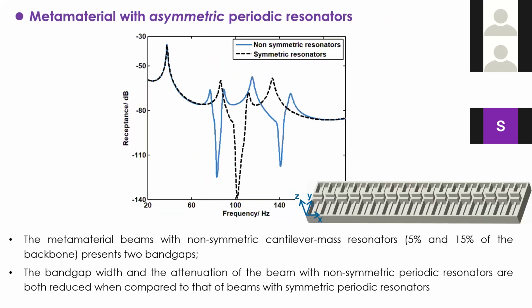And now let's look at the metamaterial beams with non-symmetric resonators. As I just explained, in each unit cell, the two resonators can be either symmetric or asymmetric. This is a comparison of the two situations. For the symmetric resonators, the mass of the resonators is about 20% of the mass of the host beam. For the asymmetric resonators, one set of resonators has a mass of about 15% of the backbone structure, and the other set has about 5% of the mass of the backbone structure.